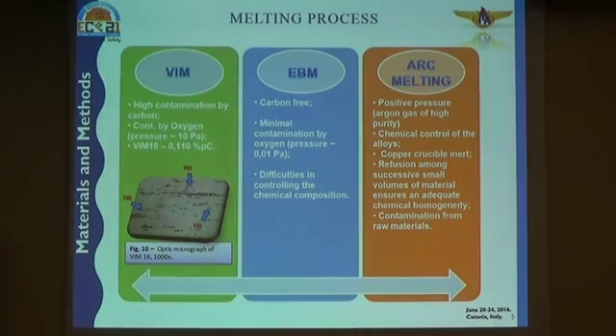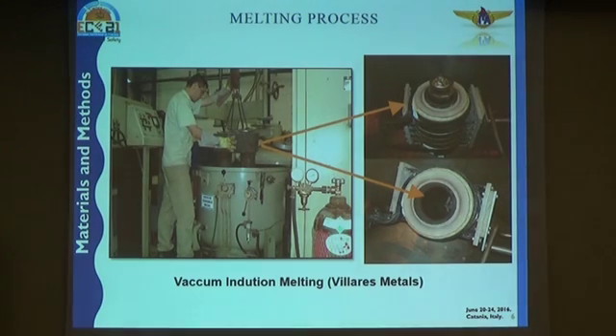Here we have three methods that we work with in our institute to melt these alloys. We work with vacuum induction melting. We work also with electron beam melting and arc melting. Of course, every technique has its good and bad points. We chose to make the alloy by the vacuum induction melting process.